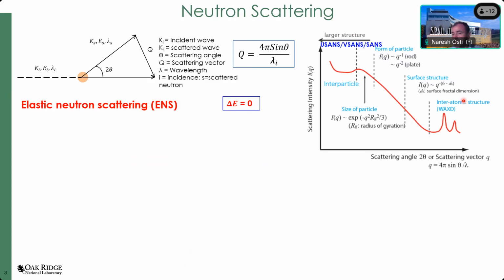And at the higher Q regime, you get the information about the atomic, interatomic structure, which we mostly resolve using the neutron diffraction technique. And the low Q regime, which is probing the larger structure, by using small angle neutron scattering or very small angle neutron scattering or ultra small angle neutron scattering, helps you to resolve the size of the particles as well.